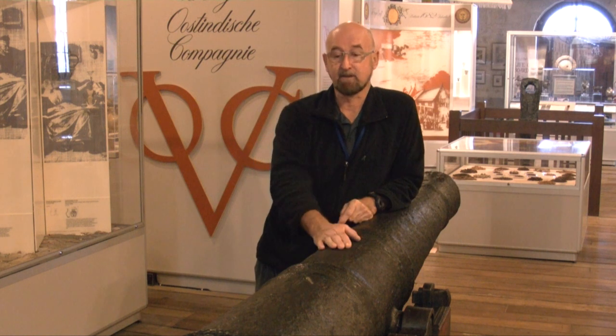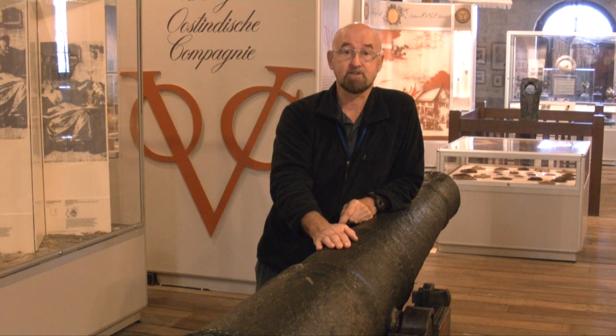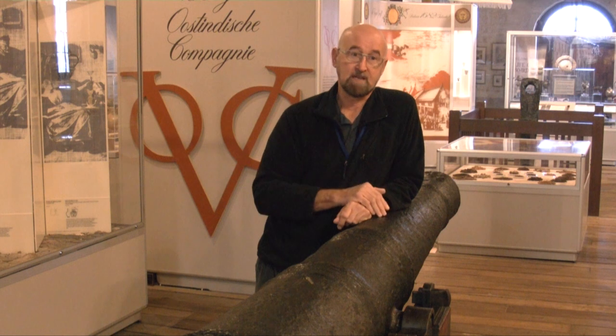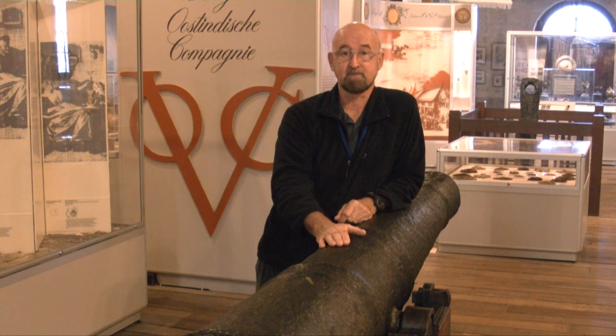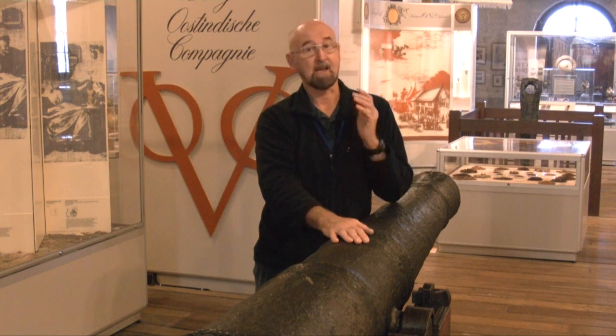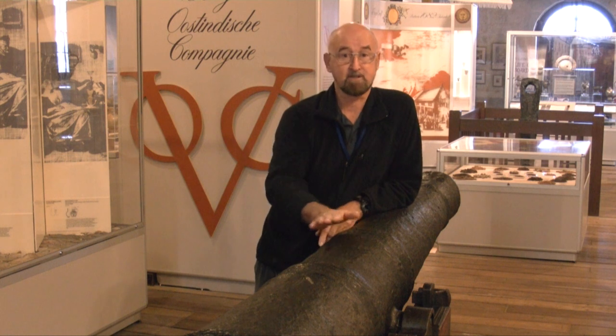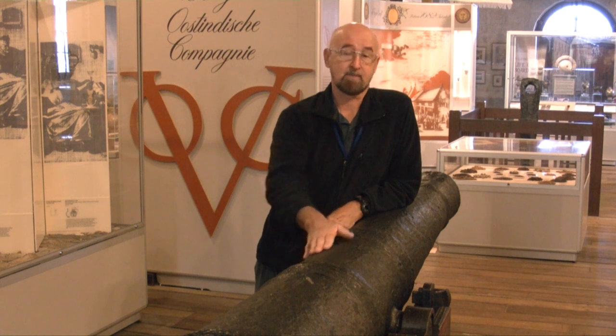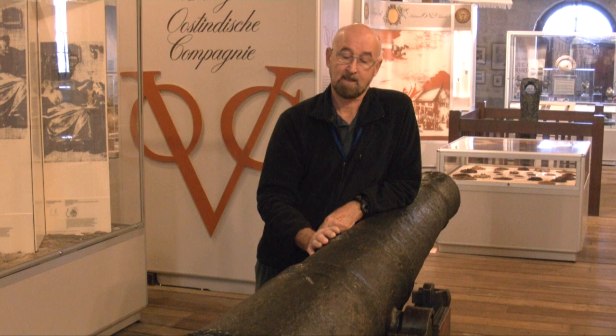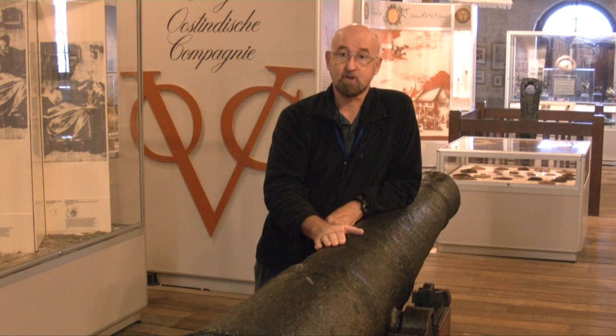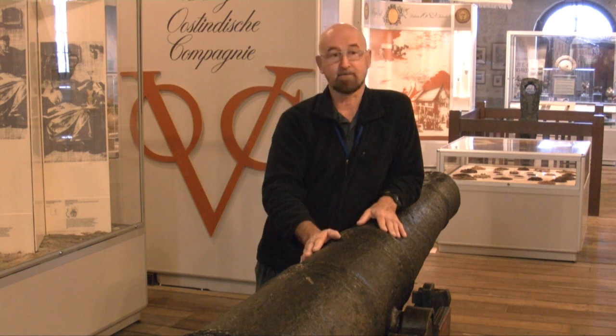Now, a lot of our cannon have come from shipwrecks, and they've been under the sea for 3 centuries. We're looking at about 1 year per century to stabilize a cannon that's been under the water. Sometimes it takes longer, but on average that's about right. For something like an anchor, which is made of wrought iron as opposed to cast iron, it can take about 2 years to treat.